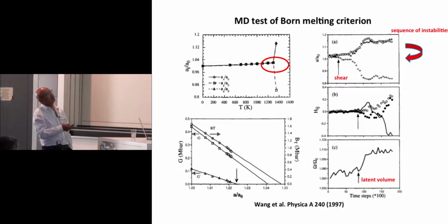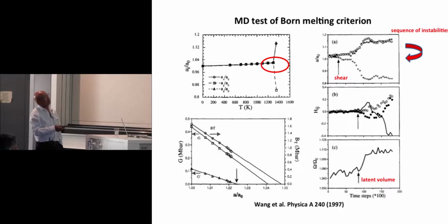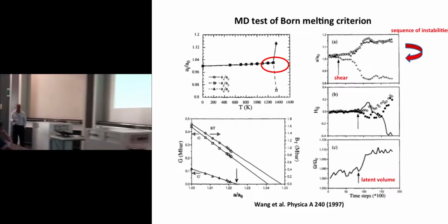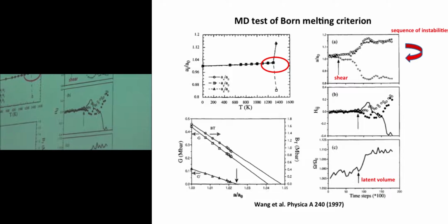instead of plotting the elastic constants like up here, you plot the Hij, the tensor that describes the shape of the simulation cell. So when it goes from cubic to tetragonal symmetry, you also know that there's a shape change, and so the shear modulus kicked in here, and the shape change didn't start kicking in until later. So there's a little time lag there, which may be interesting for some of you. But now, if you look at the volume of this simulation cell, it goes like this, and then it takes a jump.